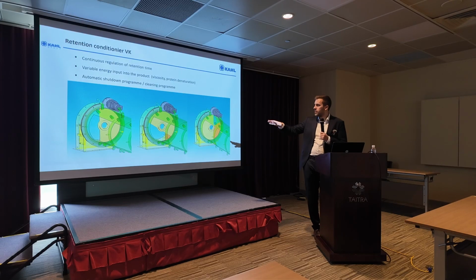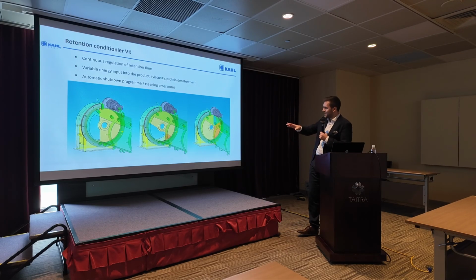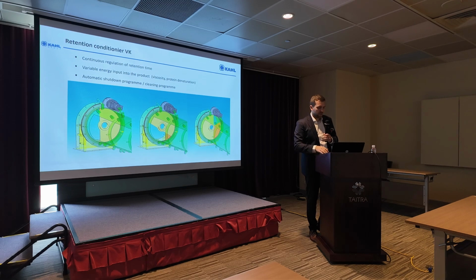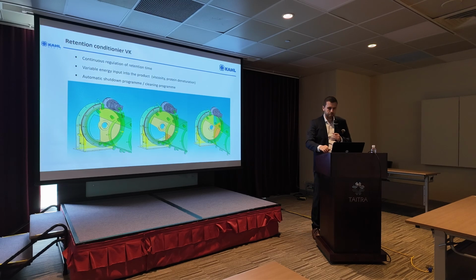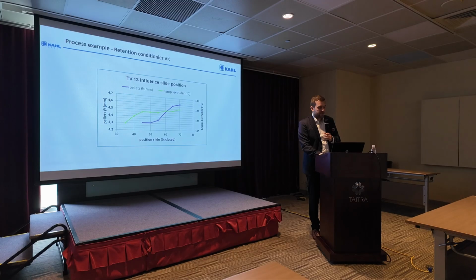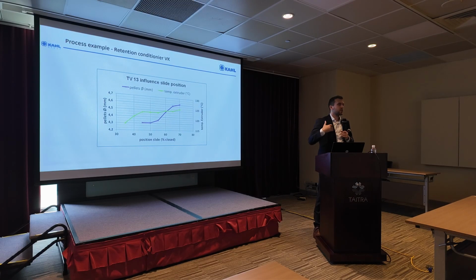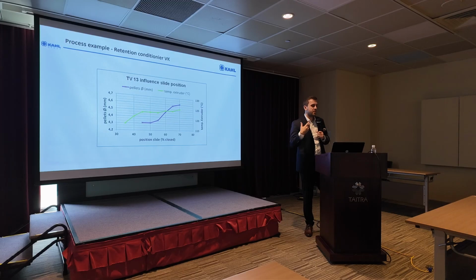So here you can see on the left-hand side, it's completely open. In the middle, it's half closed. And then here on the right side, it's completely closed or only allows a small overflow, with a higher filling degree in the conditioner. And what this does is we increase the cooking and therefore the treatment intensity in the conditioning.